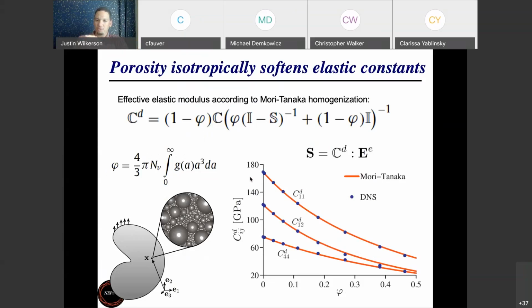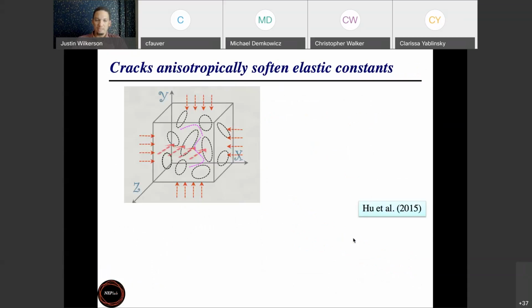That net porosity in the material does a few things. One is that it degrades the elastic constants of the material, and we can model that degradation of the elastic constants through mean field micromechanics, Eshelby type micromechanics. In this case, we're using a Mori-Tanaka method to calculate the damaged stiffness tensor, and when you compare the Mori-Tanaka method with direct numerical simulations, it's extremely accurate in this case.